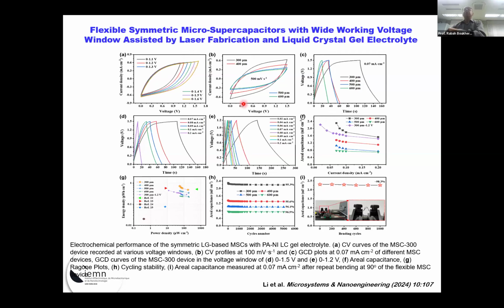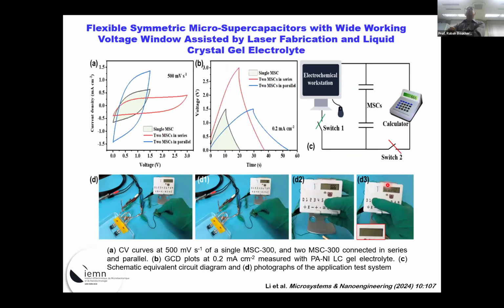But what's important now is the stability, which you keep quite good and high. You can bend the device to 90 degrees, and there is absolutely no difference. We did this up to 1,000 cycles. Of course, you can do this for more, but I think it was sufficient for the lab scale to show that you can bend, you can measure the capacitance, and there is no difference before and after, and this keeps more than 98% of the initial capacitance. The same way, we put these two devices in series, and when you charge and discharge, you can power this super small calculator.